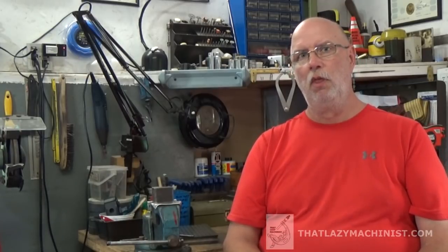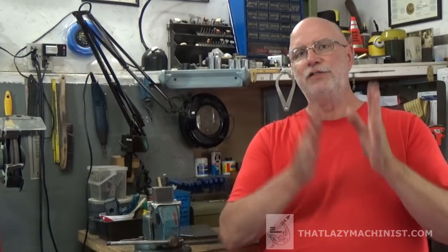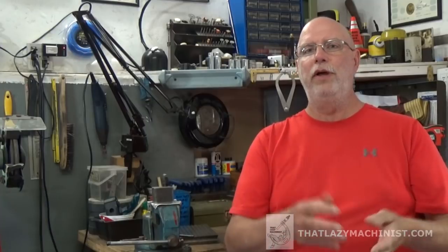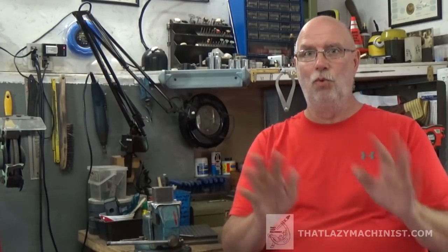The quenching in oil actually slows down the cooling process. And that is not a problem with steels like alloy steels that are made to be hardened easily. Because even if I cool down slower than water, well, I still get a hard part. I mean, when you quench, it's either hard or it's not hard. You can't harden half. You can get better penetration, but hard or soft, that won't change. So let's say I quench and it cools down slowly in oil. Well, I will get less deformation on complex parts, plus an added bonus.